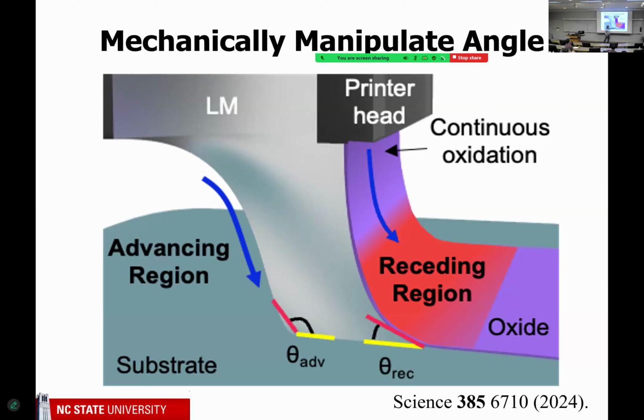But the key idea is that when we drag it, this oxide layer, when you start moving this way, you basically mechanically make this angle small enough, and this will start collapsing. Now, there's also oxide on this leading edge, and so you actually end up getting 2 layers, which I'll tell you about in a second. So this is what it looks like.